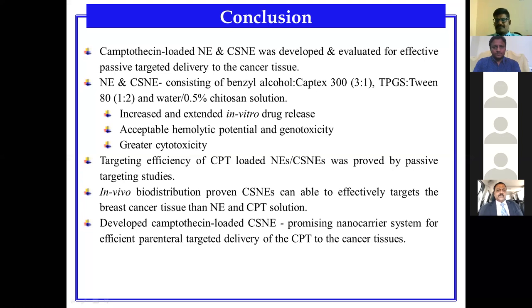One more small question, sir. Chitosans are water insoluble, right? Yes. So are there any grades? By altering the deacetylation groups as well as through an amination process, we can convert it into a water soluble or acid soluble form. By converting it into an organic salt, we can also convert it into a water soluble form.